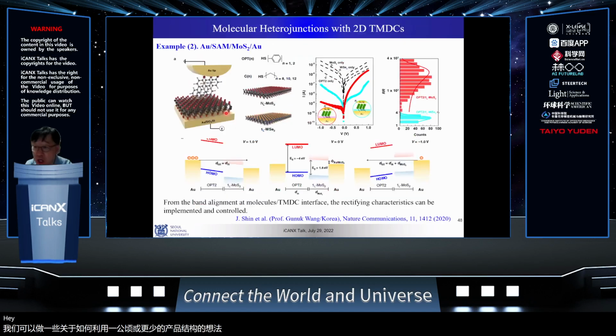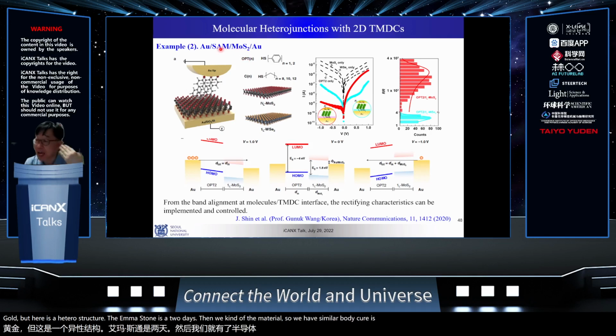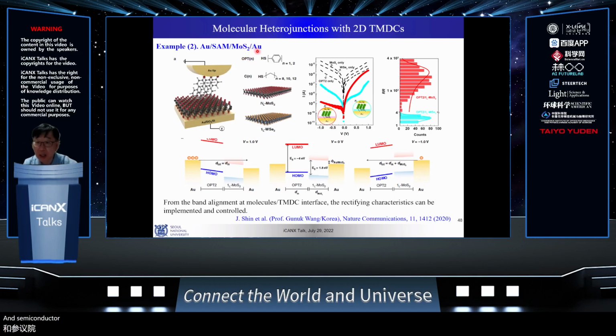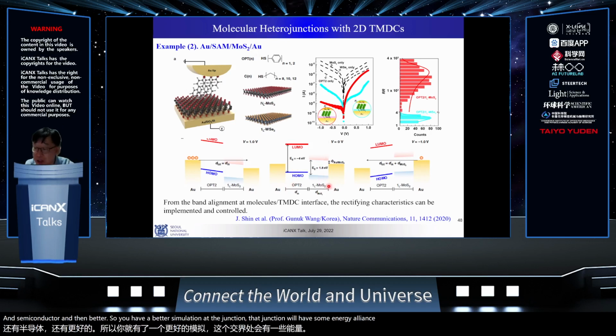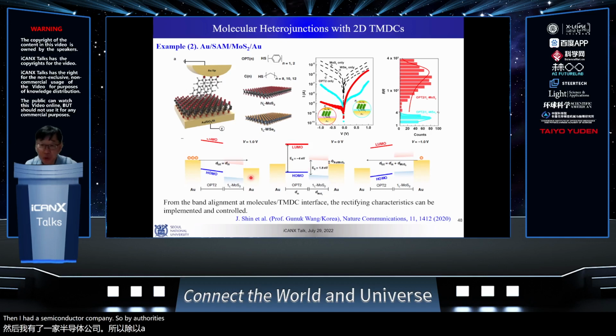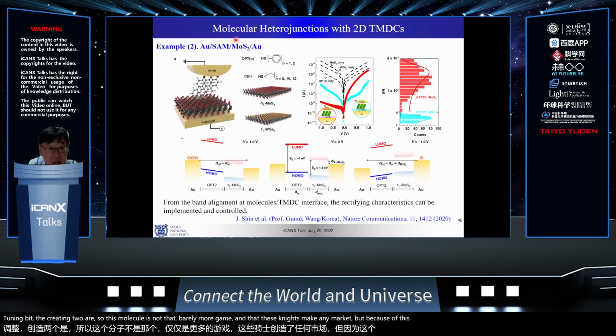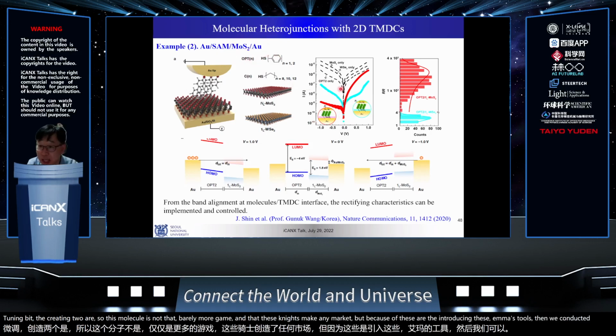Okay. And this is another example of a heterostructure, gold-molecule-gold, but here with MoS2, a 2D semiconductor material. So we have the molecule as a kind of dielectric, then a semiconductor, and then metal, so you have a metal-semiconductor junction. That junction will have some energy alignment because of the metal-semiconductor pinning, and you can easily tune it to create a diode. This molecule is not a diode molecule, it's not an asymmetric molecule, but because of introducing this MoS2 semiconductor, you can get diode behavior.